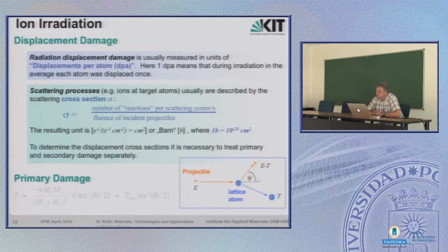And one dpa means that during the irradiation, on average, each atom was displaced once. So if you have a piece of material, put it somewhere to irradiate and stop it after it has reached the dose of 1 dpa, it means that your piece of material is completely new. It has nothing to do with your original material, since on the atomic level, each atom is on another position as it was initially. Of course, that's a theoretical point of view. In practice, you still have the same material, but after 1 dpa, each atom in this material has changed its place. Okay, let's follow on from there.